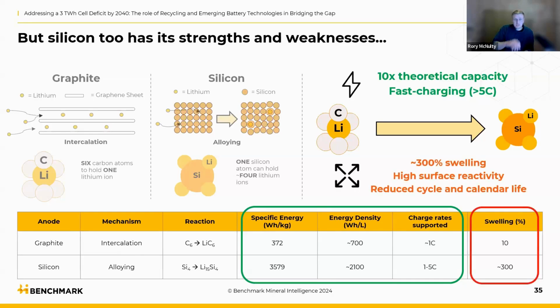However, when we look at the downsides of silicon, it's not all rosy. With this new mechanism where it takes on up to 4 lithium per silicon, we see 300% swelling of the material. That causes quite significant mechanical degradation. The solid electrolyte interface, which is formed as a protective layer on the silicon surface, can degrade, reform, degrade, resulting in constant electrolyte degradation. That high surface reactivity both reduces the cycle life or operation lifetime of your silicon anodes, and also the calendar life during storage, reactivity with either air or surrounding components, liquid electrolyte, etc.